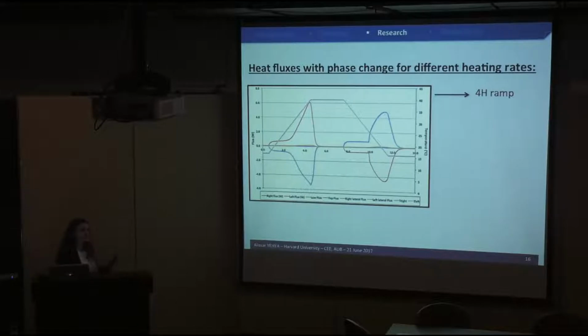This gives us an insight about the enthalpy, the shape of the enthalpy curve. Usually, the enthalpy curve is a piecewise function with a symmetrical look. But when we have these fluxes, we can see that it should be dissymmetric, with a phase of gradual melting and a more direct solidification process. Another thing that we can infer here is this discontinuity in the curve, which points to a supercooling phenomenon.